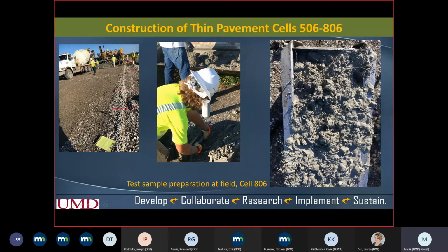It looks like good workable concrete, but look at the fibers. This was from 806 again, which had 11.7 pounds of fiber. Fibers are all over, you can see. The nature of the fiber was that it did not remain very straight. It basically followed the aggregate shape.